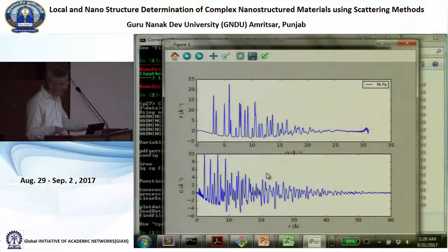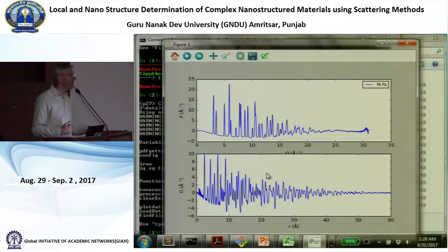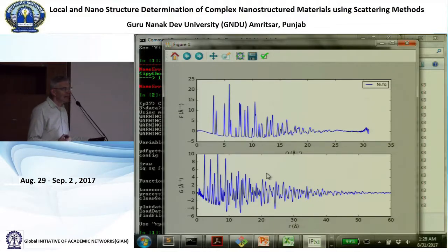Rpoly is the order of the polynomial that we're going to fit to the data before we subtract it. And the key with Rpoly is that we want to have that number large enough that we can fit all of the background, but small enough that we're not fitting any of the signal and subtracting it. And the basic idea is the units we gave for that is actually angstroms. And what you do is you look at your data and you see where the first peak is.